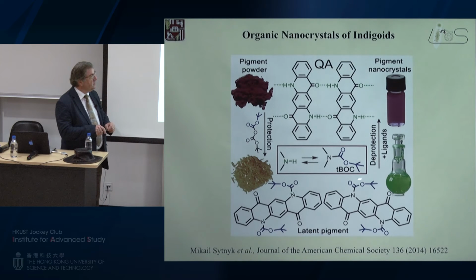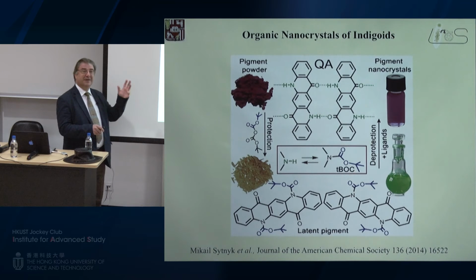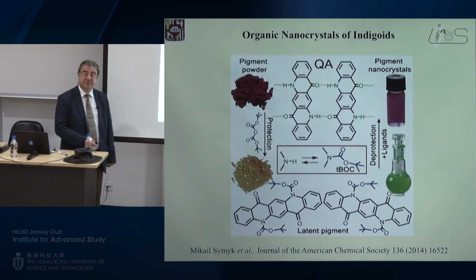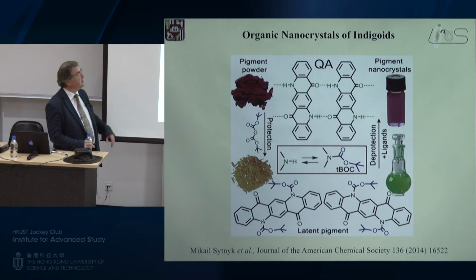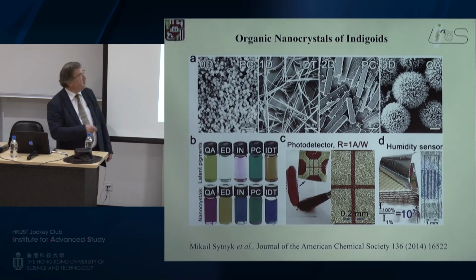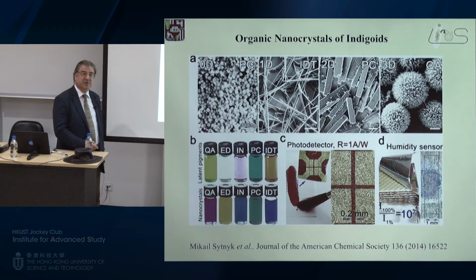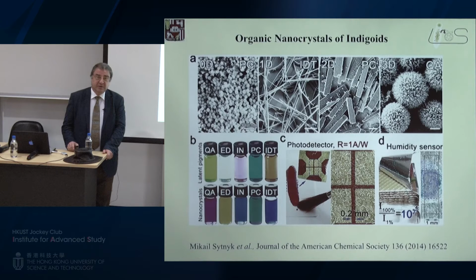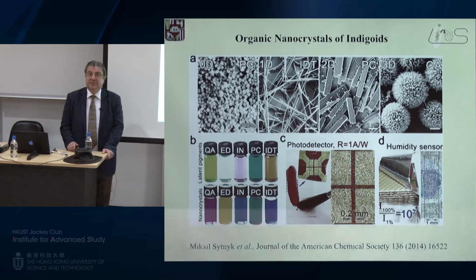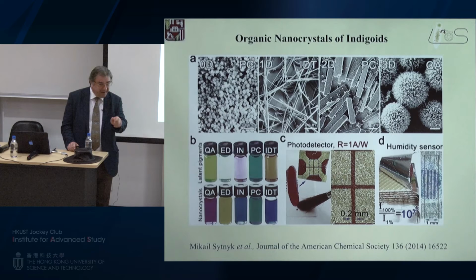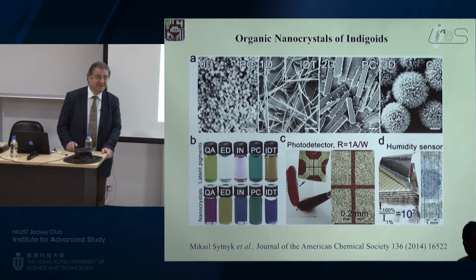So you can indeed have a chemical tool to basically turn on and off the hydrogen bond. And the interesting part here is if you take this, make a nice film cast and heat it up, for example, around 150 degrees, then this T-Boc group leaves and it comes back to the hydrogen bonded state. So this is some kind of transient chemistry, which has advantages to make these kinds of nanoparticles. This is how you make these nanoparticles using this T-Boc trick, the hot injection. But you are right, if the indigo is hydrogen bonded, this is bad news. But there is a chemistry, and again, my chemist colleagues are highly appreciated. They have tricks to turn on and off this hydrogen bond. So maybe it's a problem, but maybe we can handle it in chemistry. I hope.